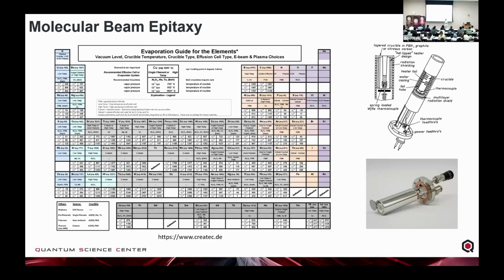The difference, though, is, of course, we are using different pure atomic materials that we can stick in these crucibles and in these effusion cells. And these effusion cells are just a crucible with a filament wound around it to get it hot. And then we just stick it inside the vacuum chamber. And you can see there's a lot of different materials that we can use this method to create, a lot of different structures. And so now we can pick and choose the atoms that we want in these materials and generate a lot of these exotic materials.